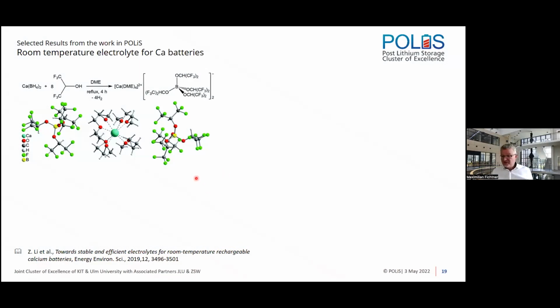So what we came up with a while ago was a discovery of an electrolyte which actually goes back to very early concepts. We wanted to have a salt-like electrolyte, not these complicated reaction systems like the Schlenk equilibrium that we had with our previous magnesium electrolytes, for example, where you can expect many side reactions and a quite complex behavior. We wanted to come up with a salt where you have the cation and an anion and everything remains stable and the cation is moving around.